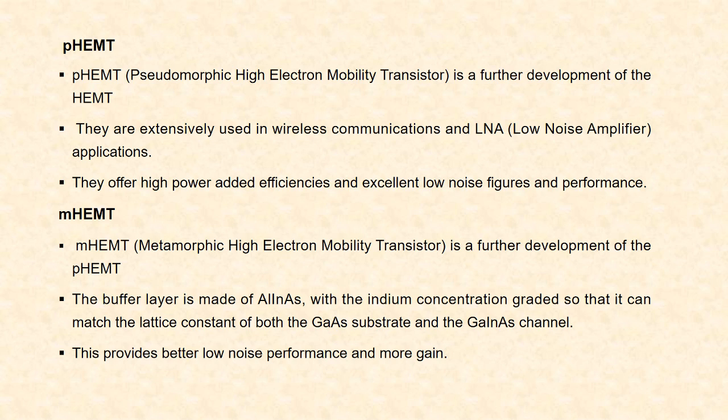Next, metamorphic high electron mobility transistor. This transistor is an advancement of pseudomorphic high electron mobility transistor. Here the buffer layer is made of aluminum indium arsenide with the indium concentration graded so that it can match the lattice constant of both the gallium arsenide substrate and gallium indium arsenide channel. This provides better low noise performance and more gain.